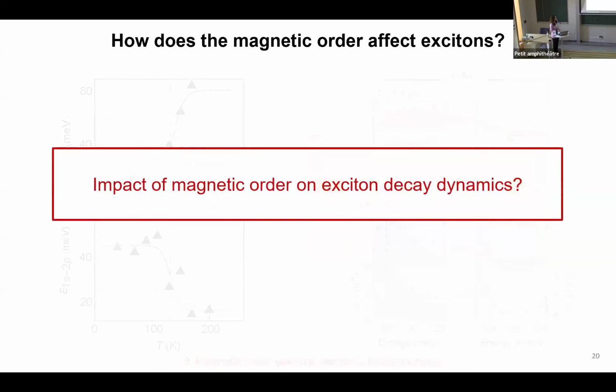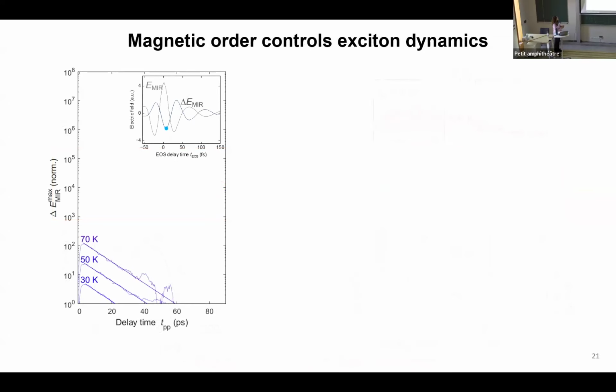Good. So now the question is, all we did is as if we studied the internal structure of excitons in a static manner, right? The pump role was just to generate these excitons. So now the other question is, how would be the effect of the magnetic field on the ultrafast dynamics of these magnetic excitons? So this is when we perform time-resolved spectroscopy. What we did is that we set at the maximum of the transmitted mid-infrared radiation, and we followed its change as a function of pump-probe delay, and we actually traced the data here.